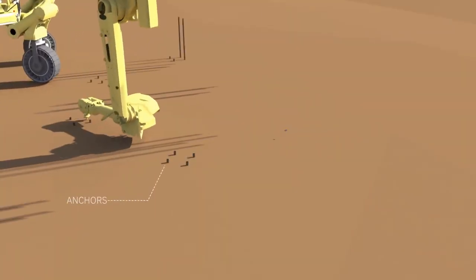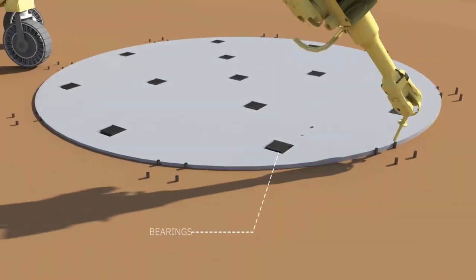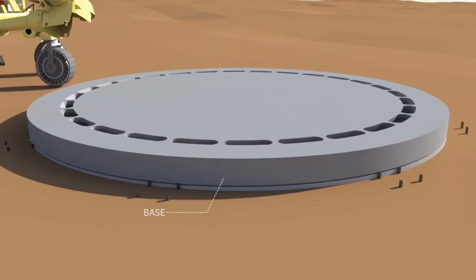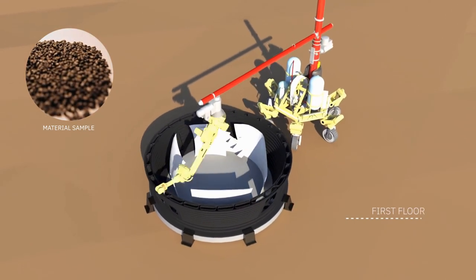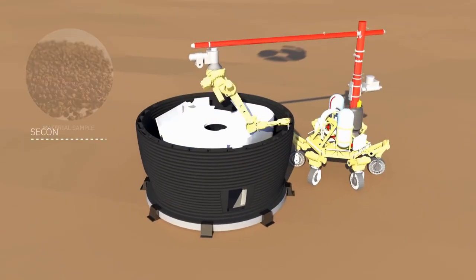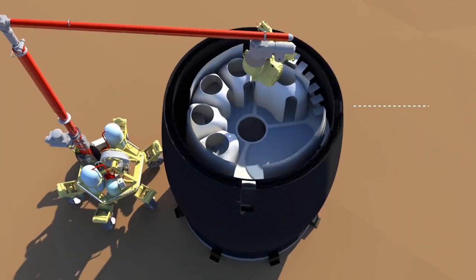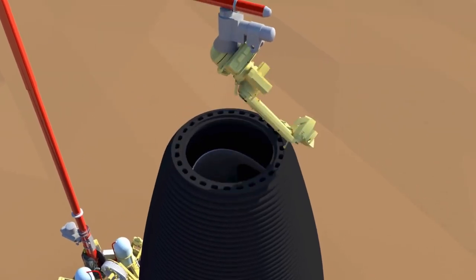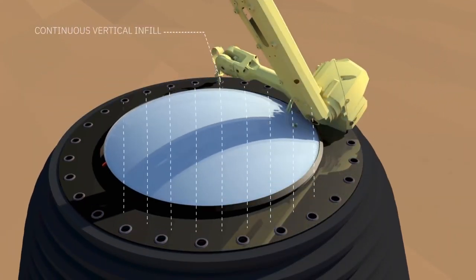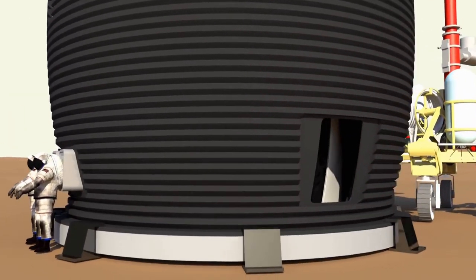In this alien environment, construction sequence and materials must be rethought entirely. We are formulating a material specifically for 3D printing on Mars, basalt fiber reinforced polylactic acid. PLA is a strong thermoplastic that is not only mission recyclable like other plastics, but mission renewable, using bioreactors fueled by mission waste. It also has among the lowest coefficients of thermal expansion among plastics, crucial to achieving composite action with chopped basalt fiber, which was added for tensile strength. Basalt fiber produced from local rock is also among the most effective insulators known. Marsha is printed in successive layers tied together with continuous pores through integrated voids, granting true structural orthotropy.